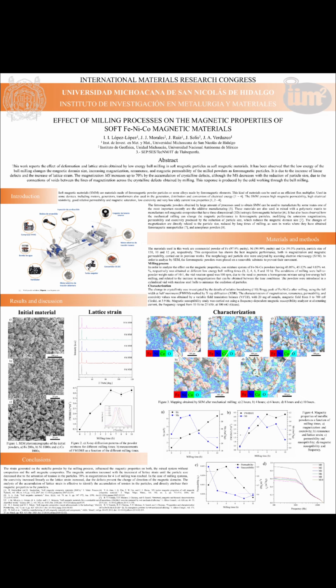It was also observed that at short times of ball milling an increase in magnetization occurred, which has been generally attributed to the formation of defects by milling, but it has not been explained in detail how these defects interact with the magnetic domains. This type of rise in magnetization is also observed in hard magnetic alloys, in which the main objective was the enhancement of magnetization and coercivity, but only an increment up to 15% was achieved. Thus, through the lattice strain analysis, it can be identified that such increment was completely related to the cold work obtained by mechanical milling and was due to the connections between the magnetic domains, increasing the magnitude of the total magnetization.